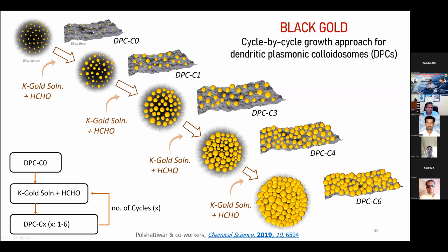What we did is we took a silica sheet. I'm showing you a silica sheet - we took a DFNS, and think about one of those fibers as this. We loaded that with gold nanoparticles, nicely distributed.